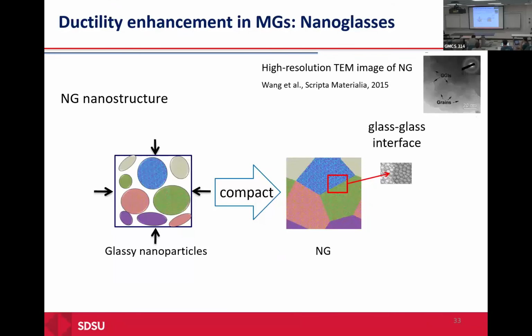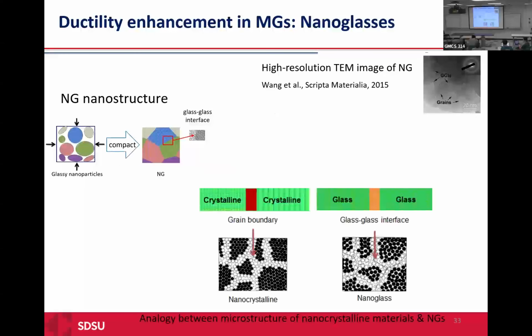Okay, these nanoglass materials are made by consolidation of small glassy grains. We just compact them, and you can see the final microstructure has glassy grains that are separated by interfaces. Nanoglass is something like nanocrystalline material, and the difference is that for nanocrystalline material, we have grains that have different crystalline structure, which are separated by grain boundaries. But in nanoglass material, we have grains that are already amorphous and they are separated by interfaces. But the microstructure properties of the interface are different from the grain.